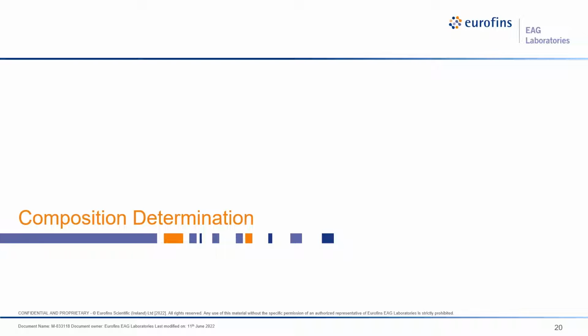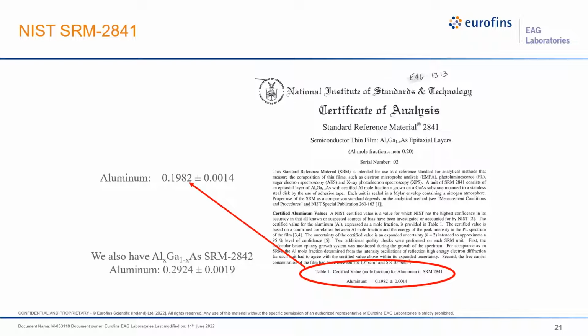Composition quantification, and in fact all quantification, is dependent on having accurate reference materials. The reference materials we use for determining the aluminum composition in VCSEL layers are all cross-referenced back to two standard reference materials, that's SRMs, issued by the National Institute of Standards and Technology. Note the low level of error in the NIST certified aluminum mole fraction, that's 0.7% relative. We consider these two SRMs as being crucial to our ability to have confidence in our reported AlGaAs compositions. Using these SRMs, we have shown the ability to determine aluminum gallium group 3 atom fractions over a wide range of aluminum compositions, as shown in the next slide.